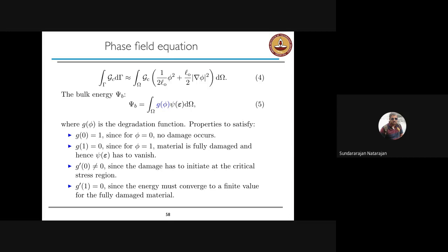And we have this bulk energy which we multiply with a degrading function, because we need to separate the regions which are completely damaged from the regions which are undamaged. So we multiply with a function called a degradation function, here represented using g of phi. And this has to satisfy certain conditions. g of 0 should be 1 when there is no damage, and it should be 0 when it is fully damaged. And there are other conditions with respect to the gradient which are necessary from a mathematical point of view.